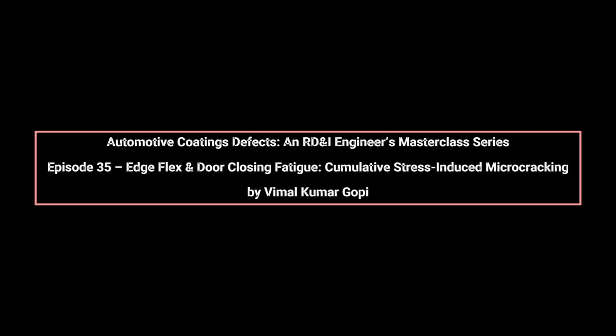At the polymer level, repeated strain causes chain scission and loss of elastic recovery. Initially, cracks are submicron in size and invisible to the naked eye. However, they form interconnected networks that reduce barrier properties, allowing moisture and contaminants to penetrate. Over time, these cracks grow, coalesce, and become visible as edge cracking, crazing, or paint lift.